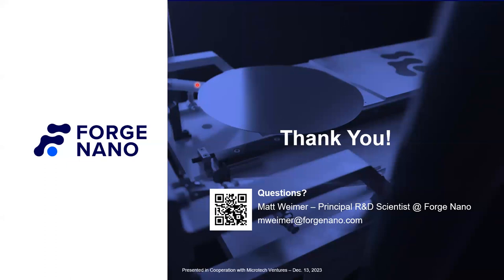But I would say more importantly, because ALD is a surface chemistry technique, if you change your precursors, you will fundamentally change your film properties at a given temperature. And that's part of what makes our CRISP conversion special: you're allowing the ALD process to occur at a different reaction pathway. So really this question comes down to what reaction pathway do you want to access? And you can access that by using a different precursor or with CRISP.